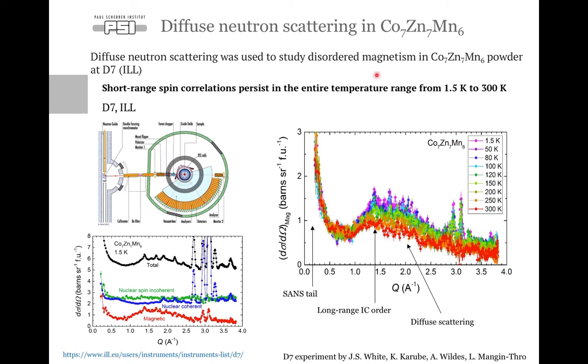Next, we use diffuse neutron scattering at the D7 spectrometer at the ILL to probe the short-range spin correlations that appear in the 776 cobalt zinc manganese powder sample. The polarization analysis in diffuse neutron scattering allows us to discriminate between coherent and incoherent parts of the nuclear and magnetic scattering and extract weak signals from diffuse magnetic scattering that can be otherwise hidden by the nuclear background or magnetic background.